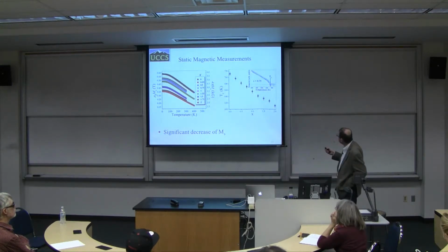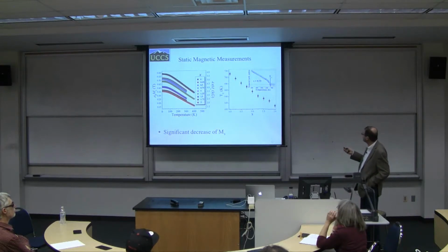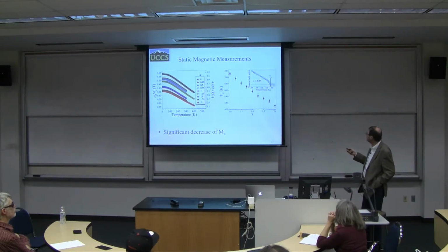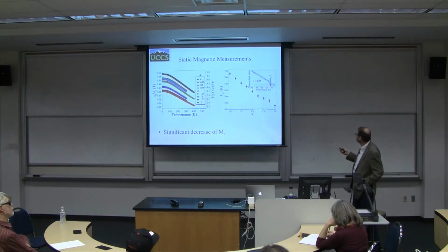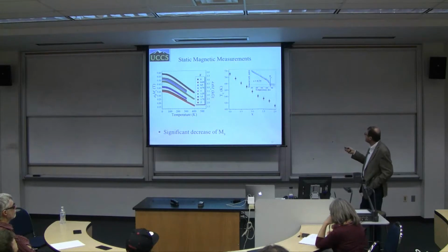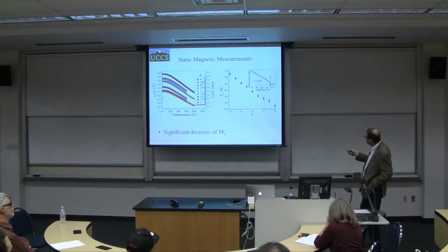And so what you see here is an individual magnetic moment as a function of temperature for one particular composition, x equals 0.75, and you see that eventually the moment is vanishing. This determines the transition temperature for this particular compound. So what I'm plotting here is Tc as a function of composition, and you can basically see it's fairly linear up to 125, and then there is a little deviation.